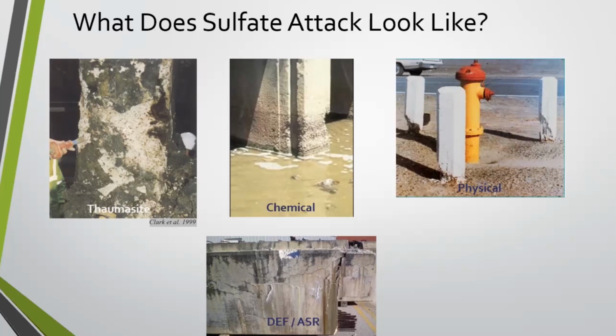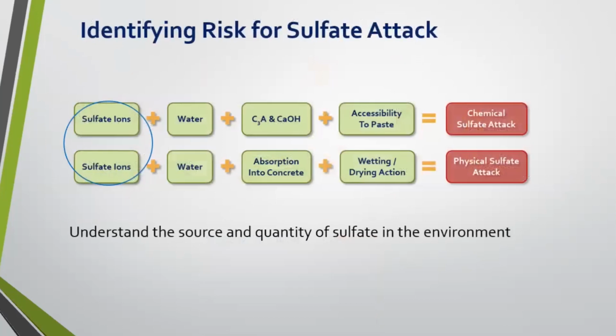At the bottom, I've got listed DEF, or again, delayed ettringite formation. This is on a mass concrete structure, and you can see the map cracking taking place there. I've got a slash ASR because, depending on who you talk to in academia, you may get some differing opinions on whether ASR is a precursor to DEF. We won't get too far into that. That's a webinar for another day. So understanding the source of your sulfates and then the quantity of those in the environment is one of the first steps, obviously.